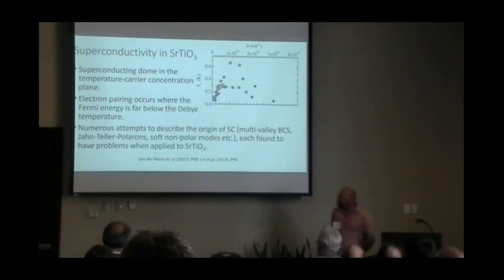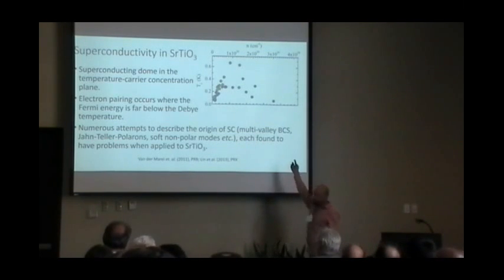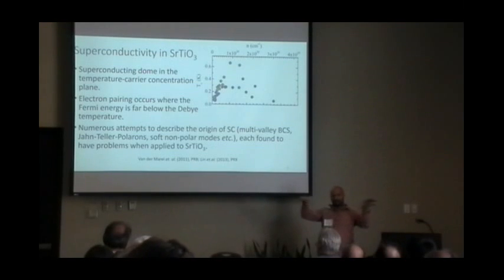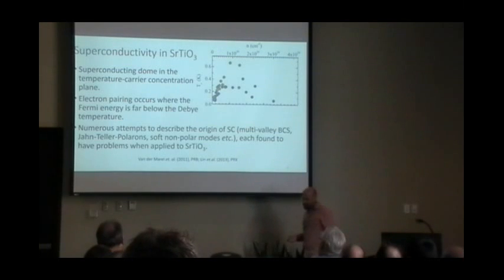There have been numerous attempts to explain superconductivity. Most of them somehow failed in that specific material for different reasons. The first one was the multi-valley scenario, so if you had several valleys, then you could increase TC, but as a matter of fact, strontium titanate has only one valley at the gamma point.